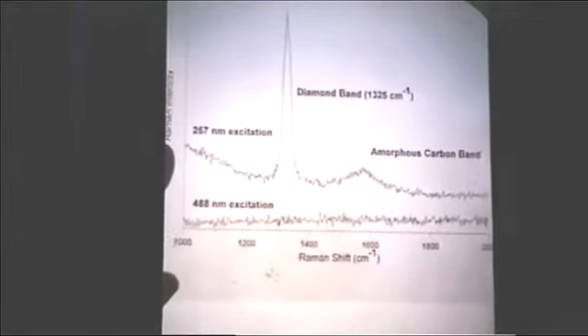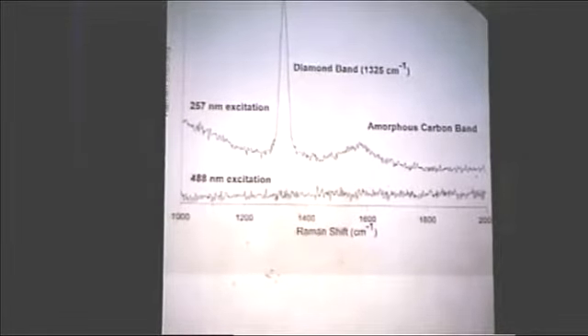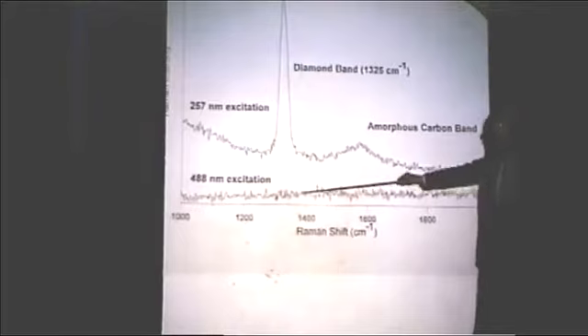Now, before I do that, though, I just want to give you a flavor for some of the other things that we've looked at. This is a CVD diamond film. You can imagine that once we found out this worked, we wanted to measure every sample we could get our hands on, right? And we were just asking people to give us samples so that we could see if it would work. It's sort of like the kid in the candy store situation. So here's an example of what happens when you try to look at this diamond film using excitation in the blue. You basically don't see anything. When you do the UV, you see a nice strong diamond band, and you also see the amorphous carbon which is around. The only thing that is appearing in this case is fluorescence.